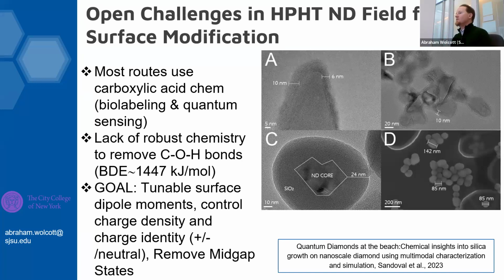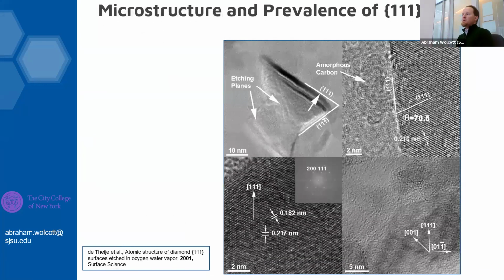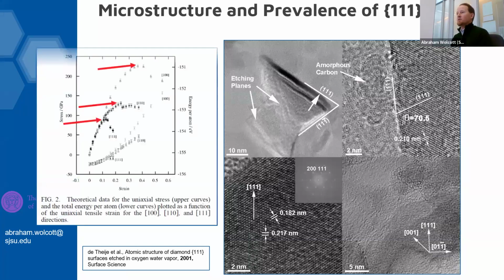On the right-hand side, these are some images of silica-coated nanodiamonds that you might all be familiar with. If we look at our HPHT nanodiamonds, we have some high-resolution TEM, and we can see that a vast majority of the facets are terminated with 111 crystallographic facets. We can do all of our characterization, looking at these edges and saying to ourselves, well, why are 111 crystallographic facets overexpressed within this material?